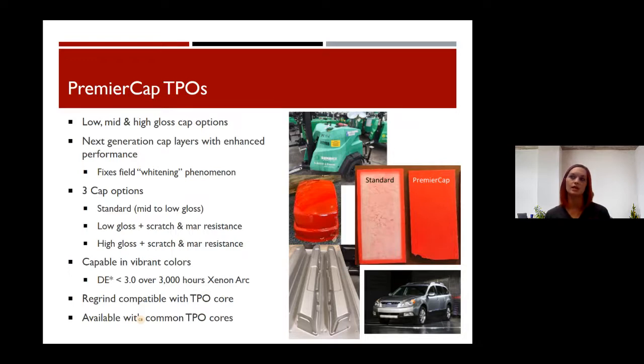We embarked on a long project to figure out what it was because it didn't make sense. We had UV in there. These things were weatherable. They were using color fast pigments. We learned a lot and found out that the root cause wasn't truly weathering. The properties were there. It was just a surface phenomenon, happening post-forming, where some of the mineral fillers at the surface were locally enhanced, where there were just more of them.